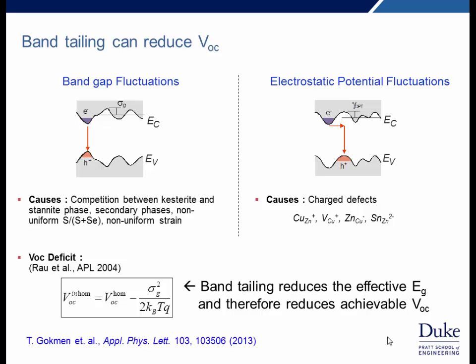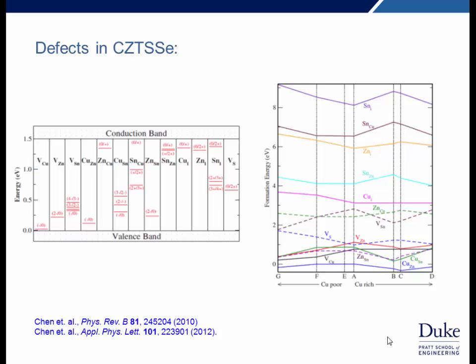Using simple models, one can predict how much these fluctuations will reduce the VOC. Depending on the model, the functional form will be different, but in general, the amount of reduction is going to depend on the amplitude of these fluctuations. So we saw why band gap fluctuations may be important. Why might we have charge defects in this material?